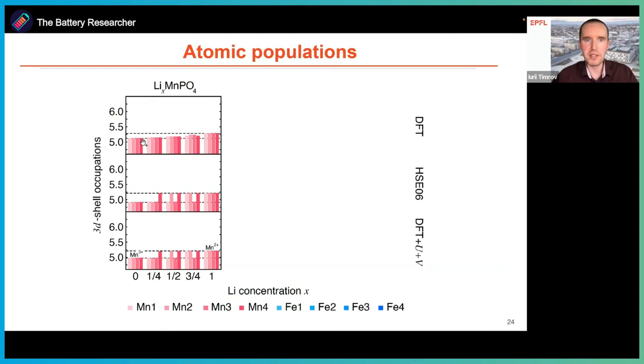You see that on average, all manganese increase their occupancy little by little, which is not correct. Instead, the other two methods, which are much more accurate, show what we call digital change in the occupations. We see that just one manganese at a time shows the jump in the occupation. So it changes the oxidation state from 3+ to 2+, one at a time. So we call it digital change. And this is consistent between DFT+U+V and the more expensive method, hybrid HSE06.